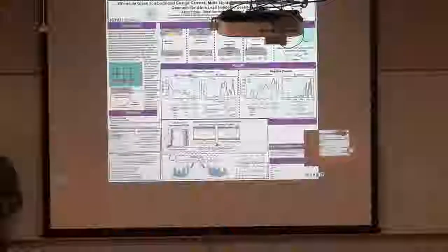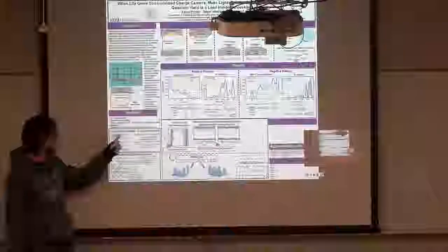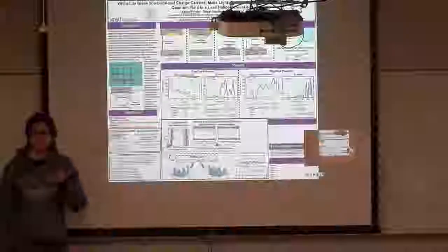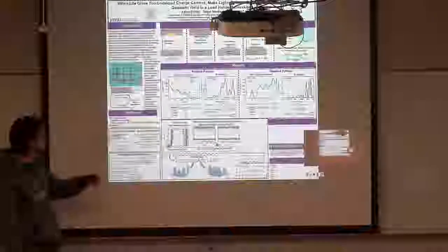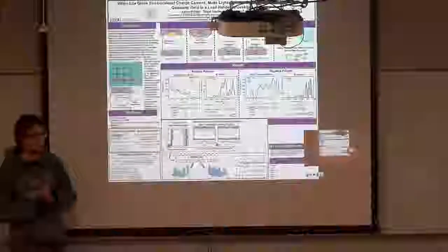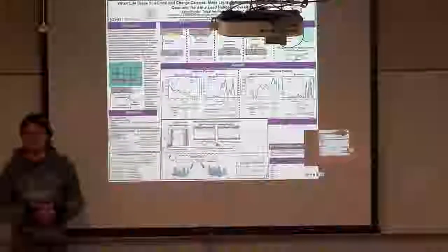So traditionally, when people were first working on these problems, there's a man named Fröhlich who attempted to solve this problem. The Hamiltonian he came up with was kind of the standard Hamiltonian. So you have the electron degrees of freedom, your independent phonon degrees of freedom, and then polaron formation is the coupling between electrons and phonons. So you have a cross term in there, and then these are just the convenient second quantization ways to represent these. So you have your electronic energies, your phonon energies from your creation and annihilation operators, and then you have the off-diagonal elements which couple electronic and nuclear degrees of freedom.